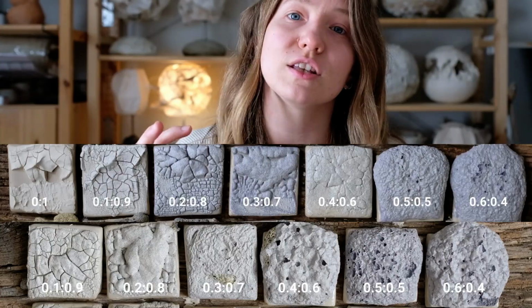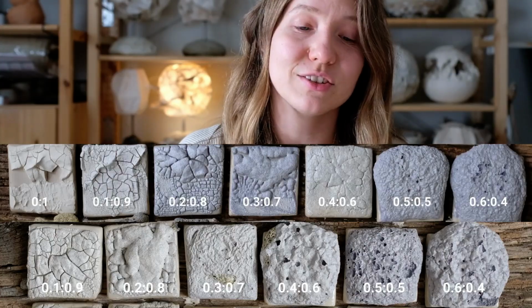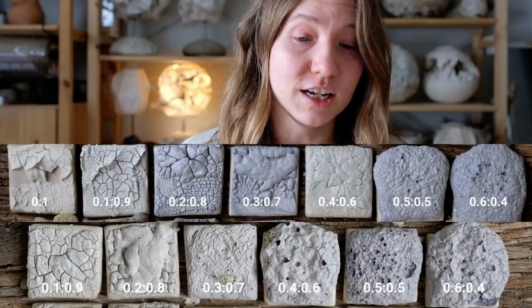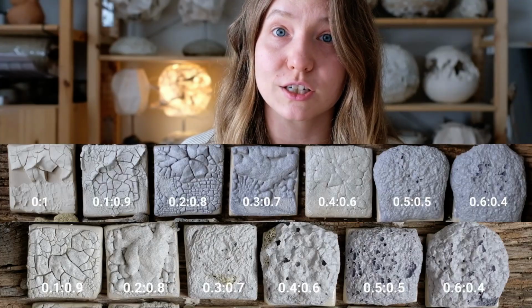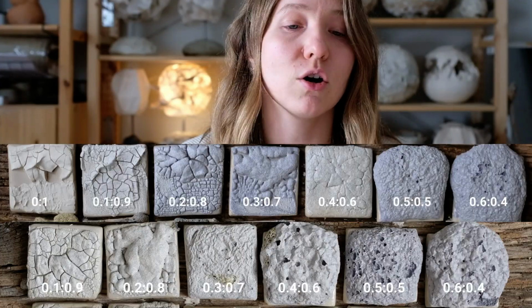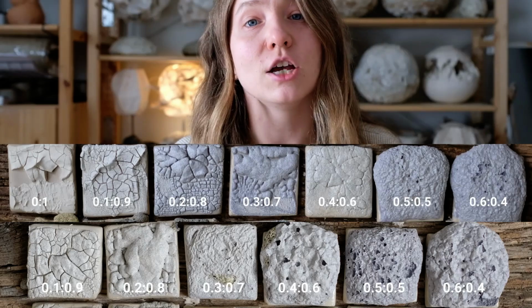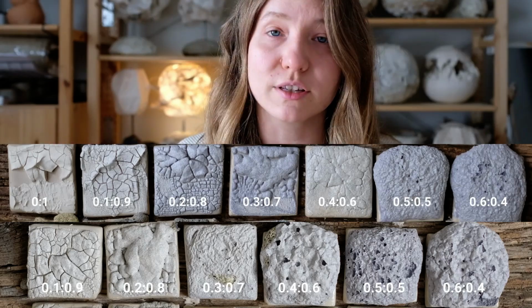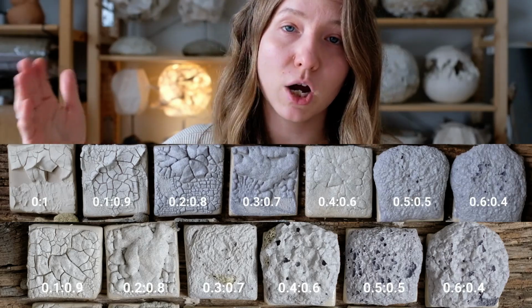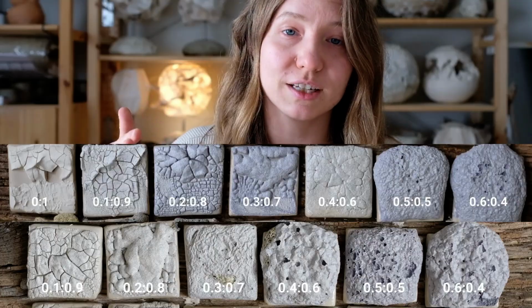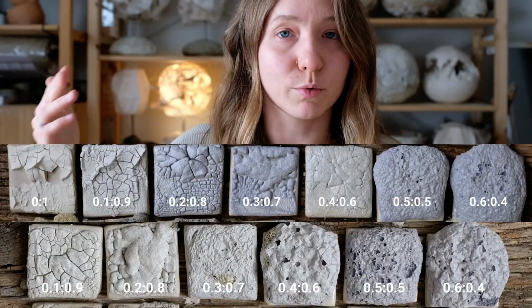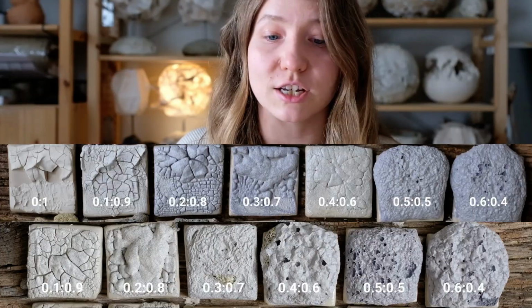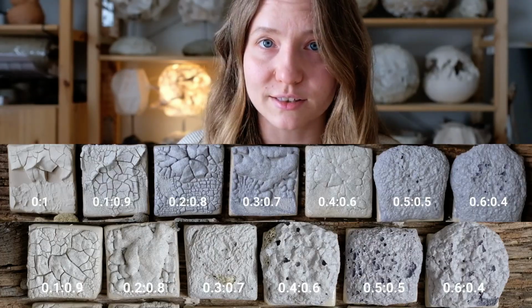The surface tension was really high, so it fell off the test style just because there was literally almost zero melting, because the melting temperature of this combination of ingredients should have been a lot higher than it was on the specific test style. As we keep going, as we move towards 0.3 to 0.7 and then 0.4 to 0.6, the more reaction there is, the puffier the glaze there is.